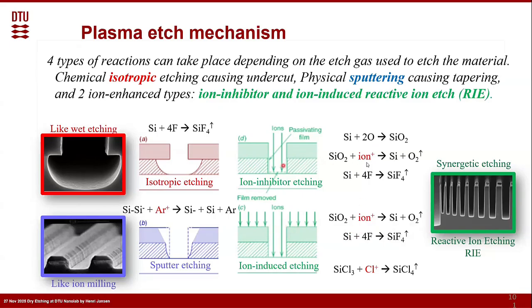Whereas in this case, for the ion inhibitor, because we still have this huge amount of fluor radicals, as soon as the bottom is freed, it can really go that every ion can etch like 100 times more silicon.